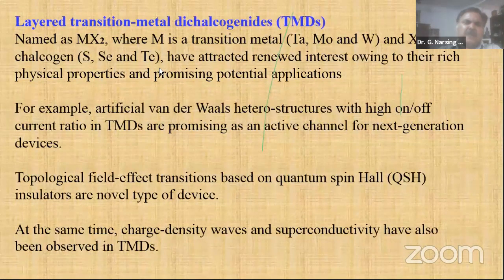The purity of these materials is most important. Most of these studies show different properties depending on the quality of the material. They have attracted renewed interest owing to their rich physical properties and promising potential applications, for example artificial van der Waals structures. In this layered transition metal dichalcogenide, if there are a few layers, we can remove a layer without any chemical. Just stick tape on it and pick up, and you will get one layer of the layered transition metal dichalcogenide. That is because of the van der Waals heterostructure.